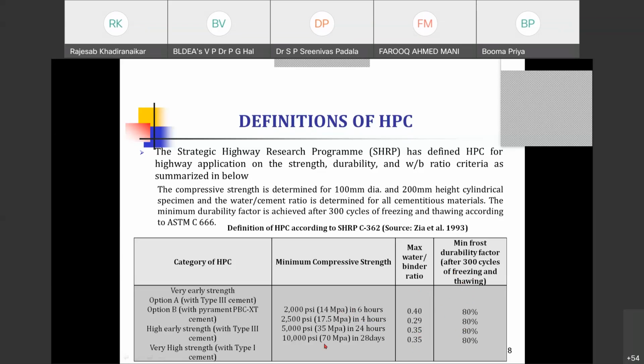So in 6 hours, SHRP expects around 14 MPa, and then 17.5 MPa in 4 hours, and around 35 Newton per square mm in 24 hours, and then around 70 MPa in 28 days. This is the high performance concrete. They accept this according to SHRP.